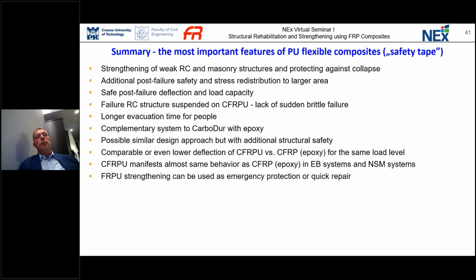Also, if we use some kind of carbon fiber strengthening, this kind of solution with flexible bonding is complementary to classically used epoxy resin, as was presented, so it can be used simultaneously to increase the post-failure safety. And also, if we compare fibers bonded with flexible adhesive and stiff adhesive, we can say that we obtained a lower deflection having the same load when we used flexible bonding. And also, when we use near surface mounted systems, in this case, flexible bonding is as effective as epoxy resin adhesives.